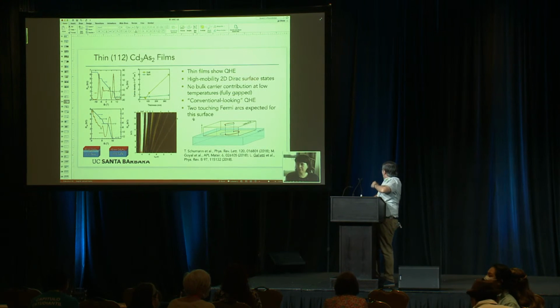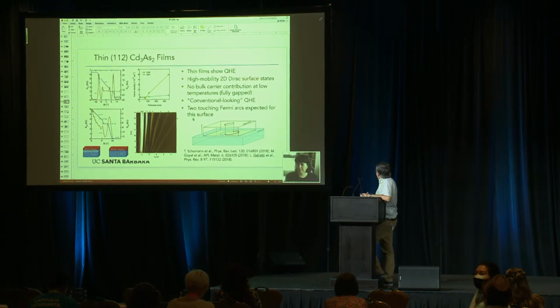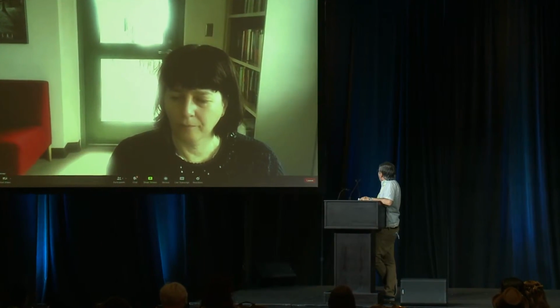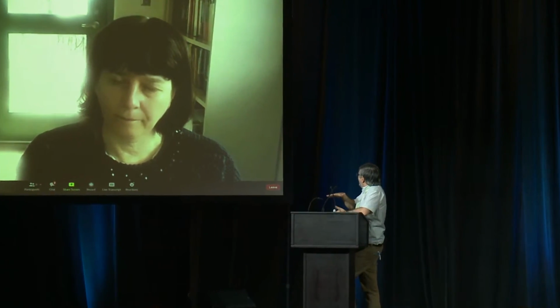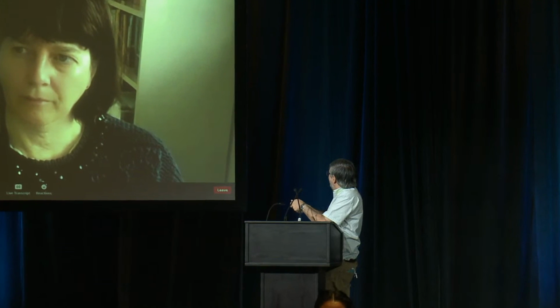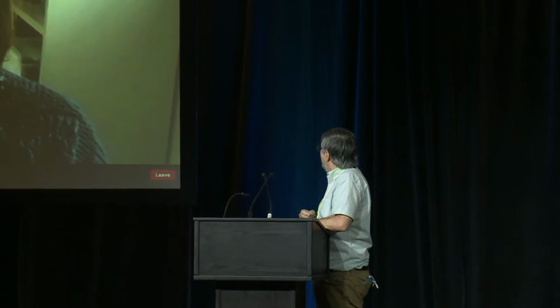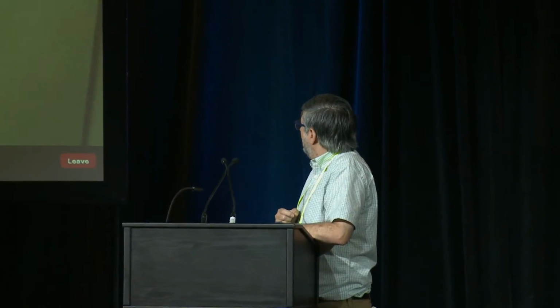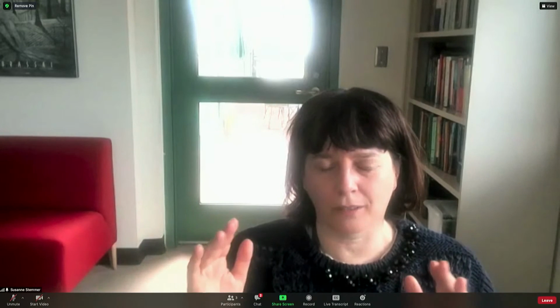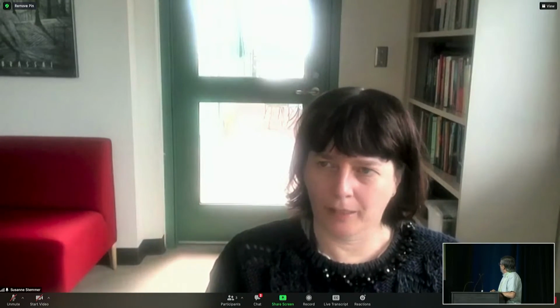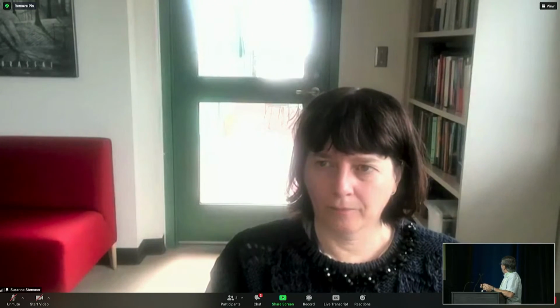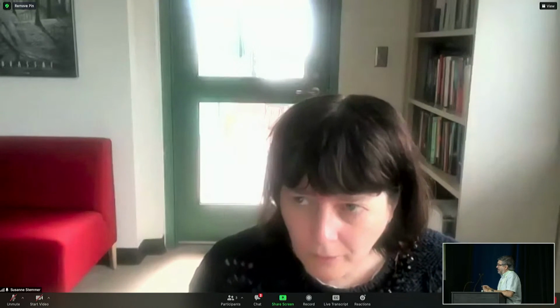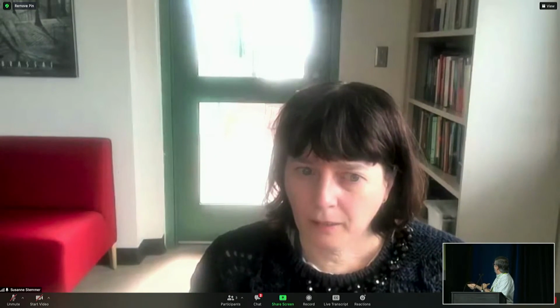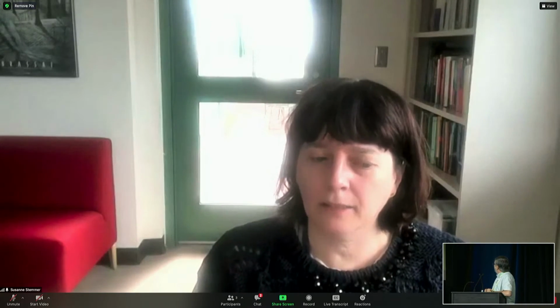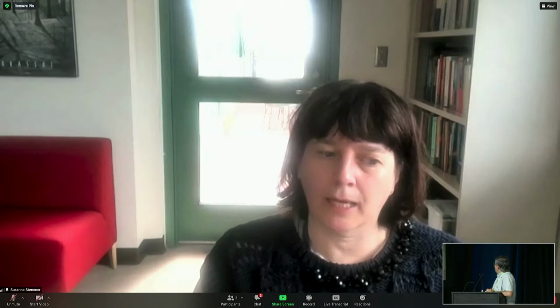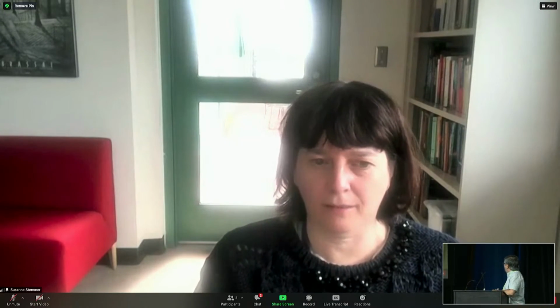If I may ask a question, in the part where you tune the properties with the tensile strain or the compressive strain, the strain is in plane, right? I mean, you are not compressing along the thickness of the film. It's an in-plane biaxial stress, but of course the strain is triaxial. So if we apply a compressive strain in the plane, it expands out of plane. Is it an isotropic strain you apply, the same in all directions? It's in plane, so in plane it's a biaxial strain, the same, and then out of plane it's dictated by whatever the elastic constants say.